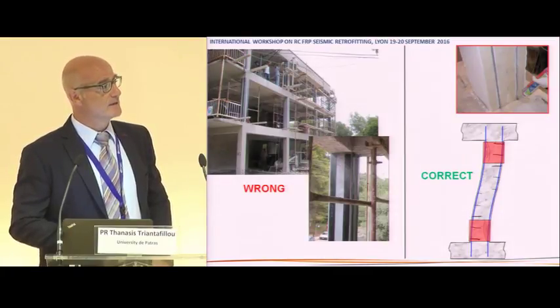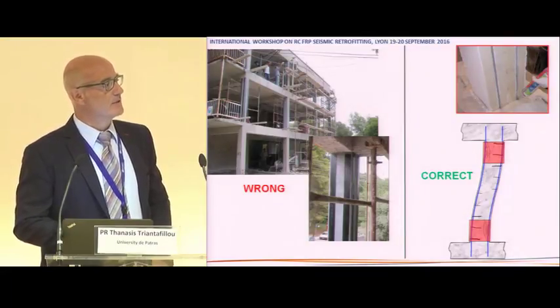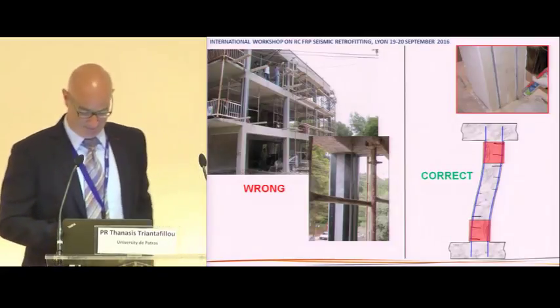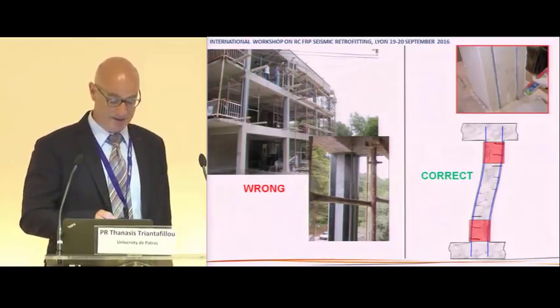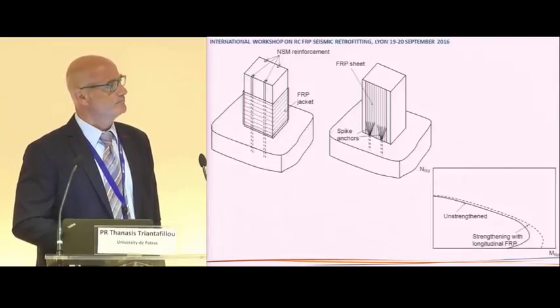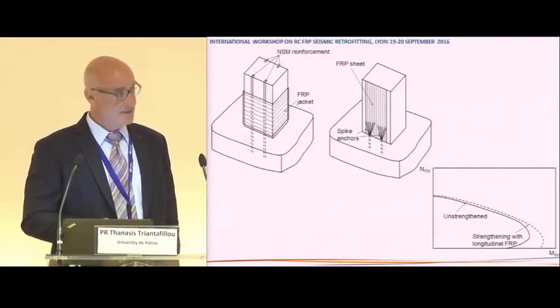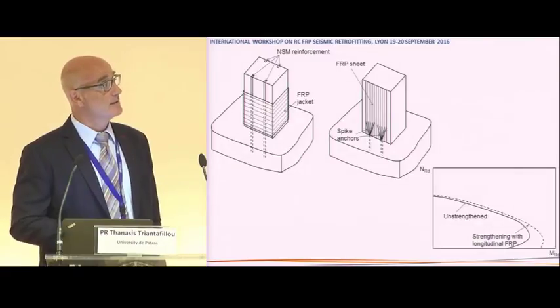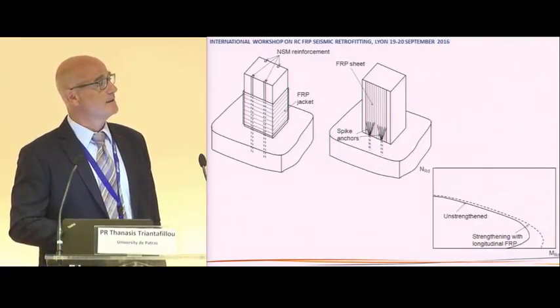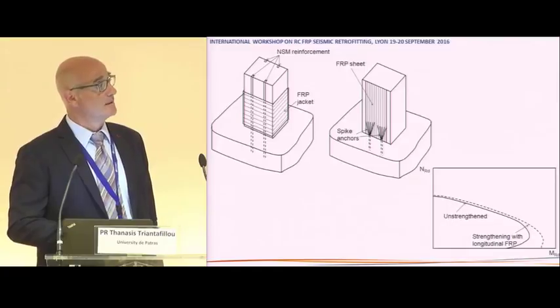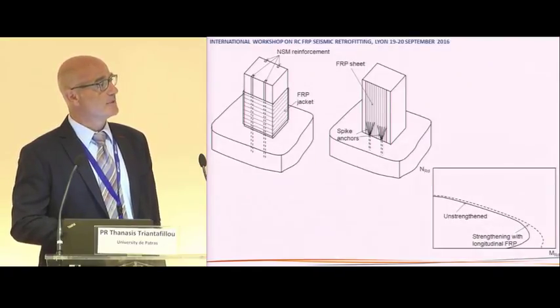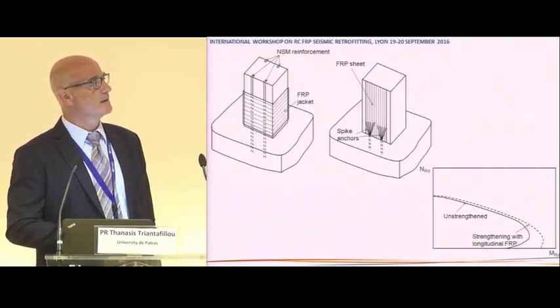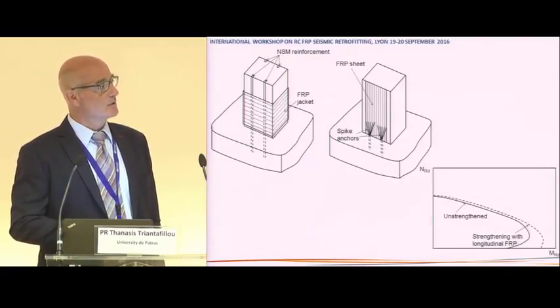So if the objective is to do flexural strengthening of columns, we need to remember that we must extend the material through the joints, slabs, foundations, whatever. Because typically this is where moments are high. There are a number of ways to do it. One is to use near surface mounted reinforcement, that is FRP or even steel rebars placed inside grooves. Or we can use fabrics with the fibers in the longitudinal direction of columns, anchored using spike anchors.